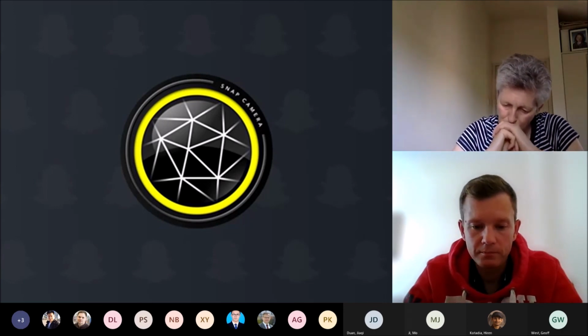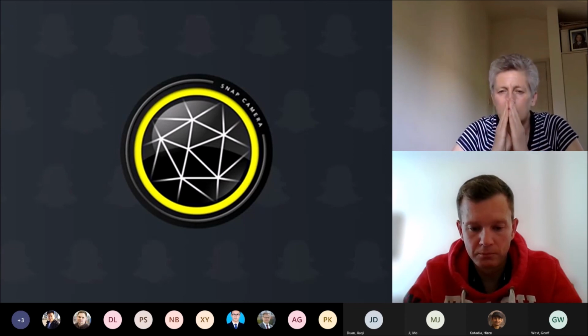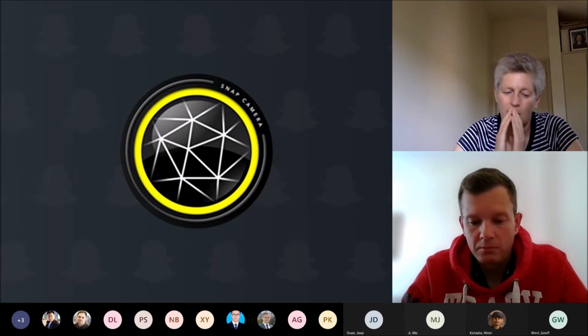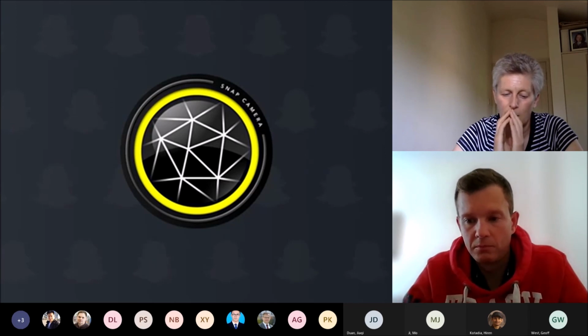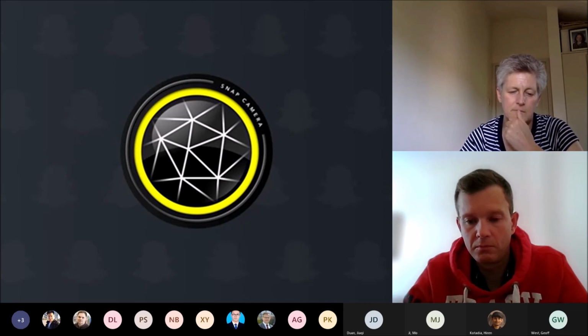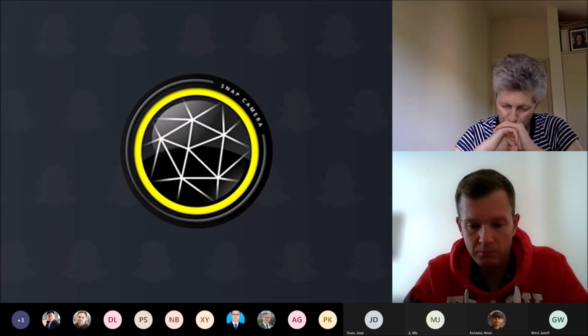Sorry. So I was thinking, would your grain morphology also have an impact on your volume fraction? Because I remember from one of your EBSD images that you have very elongated grains, and it seems that a very flat surface going along the rolling direction would facilitate the Goss texture formation, or go against it. That's my question. Would it have an effect as well?